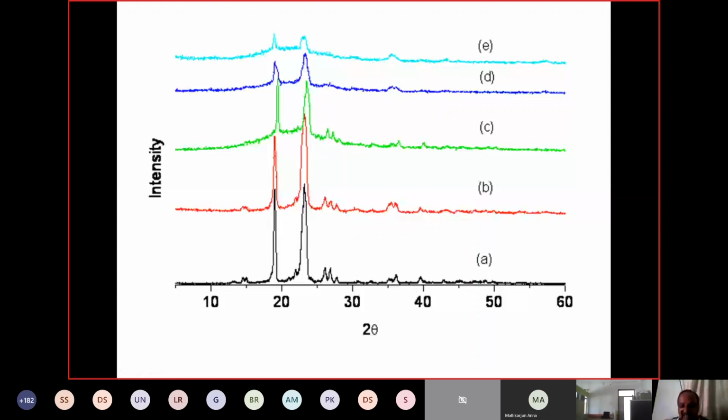So the important property is what? Disrupting the crystal nature, which is increasing the amorphous nature, which is very much required for the transport property. Okay. So you see here, the characteristic diffraction peaks are apparent between 18 and 30 degrees, between these two. So it indicates the semi-crystalline nature of that polymer, right? The sharp diffraction peaks found in pure PEO become less prominent in complexed PEO films, whereas the intensity of these peaks is decreasing and broadening, which indicates the complex formation between the PEO and the LiClO4.